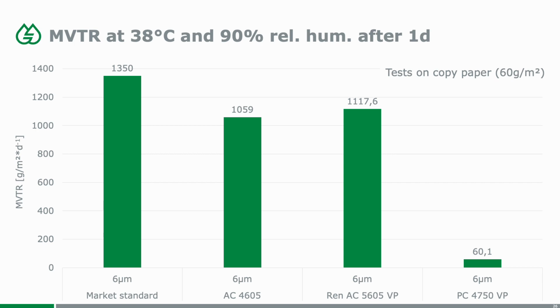So here we do the tropical test, MVTR at 38 degrees centigrade and 90% relative humidity after 1 day. And again, we do that on the copy paper with 60 grams per square meter. And now you can see that the paper was not tested anymore, because then the numbers will go sky high. The market standard now performs at 1350. The 2 single-phase acrylics that we provide are around 1000 grams per square meter per day. And the PC 4750 is still very, very low at 60 grams per square meter per day. And I once again stress, it's just done on copy paper.